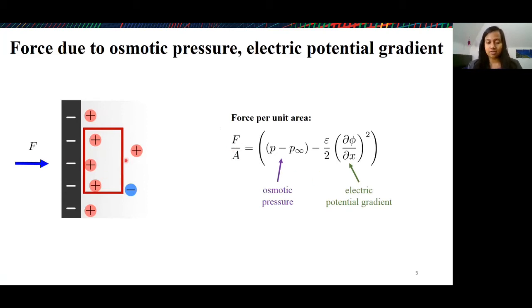Additionally, across this diffuse layer, there's a potential gradient. That is, the electric potential drops from being whatever is the applied voltage at the surface to just zero in the bulk. And so most of this transition occurs in this diffuse layer. And so you have a sharp electric potential gradient. And this contributes to the total force through the Maxwell stresses. One thing I want to point out is that the force depends on the square of the electric potential gradient. So the force is inherently nonlinear in the electric potential gradient.